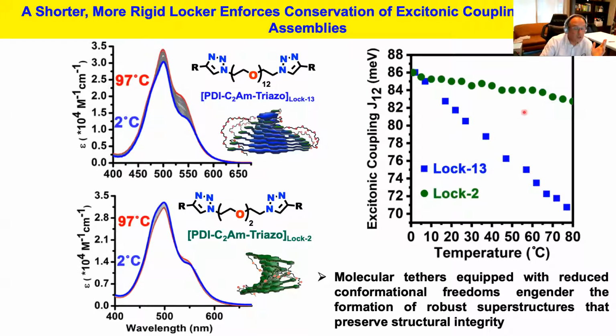It's pretty interesting to see that when we are locking the supramolecular polymer together with a shorter locker, while you do witness a small decrease of the excitonic coupling as a function of temperature, the change is nothing compared to what we have seen for the lock 13. That tells us that when we are dealing with a more rigid chemical locker, we are probably to some extent enforcing a nanoscale object that is way more robust and has a limited degree of freedom when it comes to slippage, for example, of the PDI stacks.